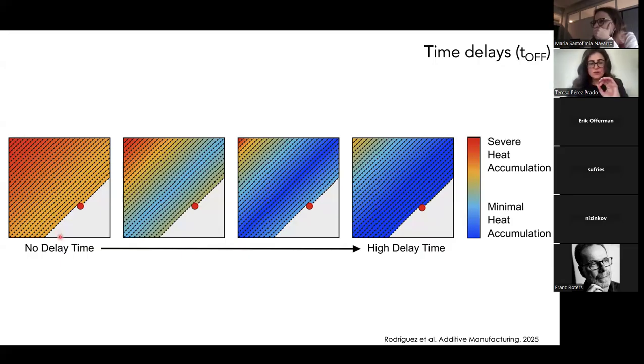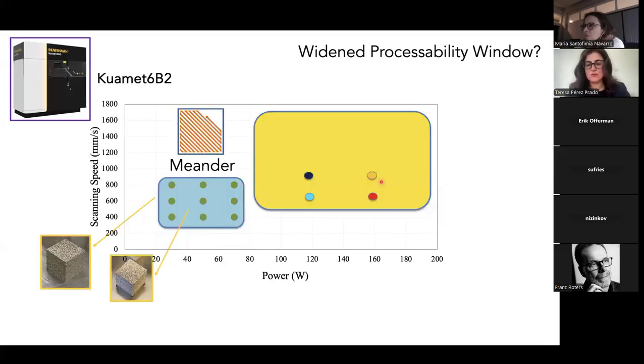The delay time means that when the laser comes to the end of one of these tracks, we shut off the laser for some time. Then we turn it on again, and the laser comes back. And then we switch it off, and so on. So this is switch off time after each track. If we increase the time delay, in theory, the idea is that we allow some time for the layer to cool down and to accumulate less heat. And hopefully, this was our hope, that this can serve the purpose and solve the challenge that we have. So let me show you how and to what extent this was successful.